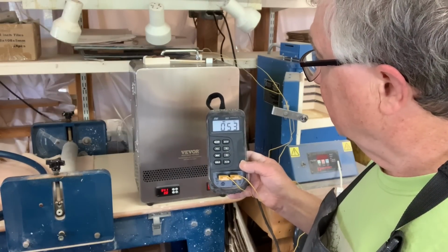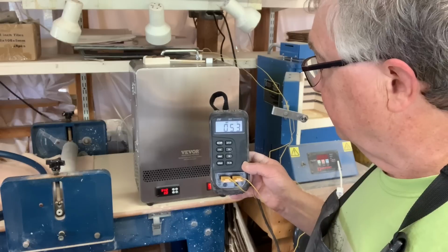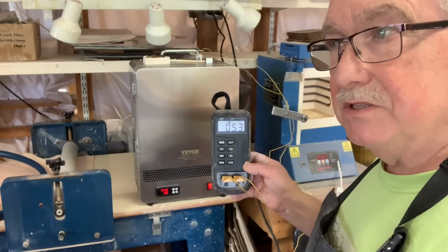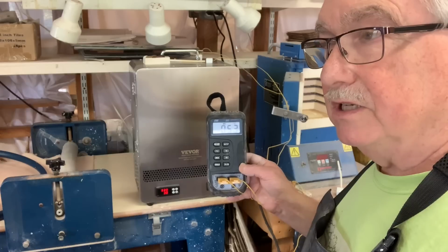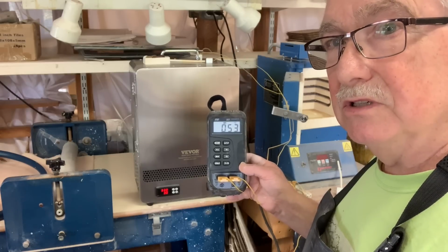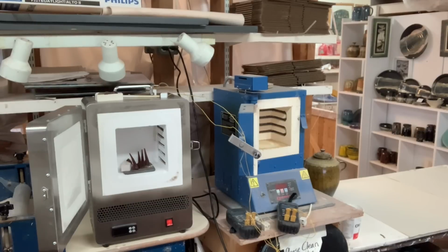The thing I wanted to show you is that we have the thermocouple laying on the top is reading 53 degrees centigrade, even though it's right at Bisque temperature inside. So the kiln does not get super hot on the outside. Okay, 06 bent over, hooray! 05 was just beginning to start bending, and the other cones weren't bent at all. So this temperature of about 940, 950 is perfect for a Bisque firing. So at least we've established that.